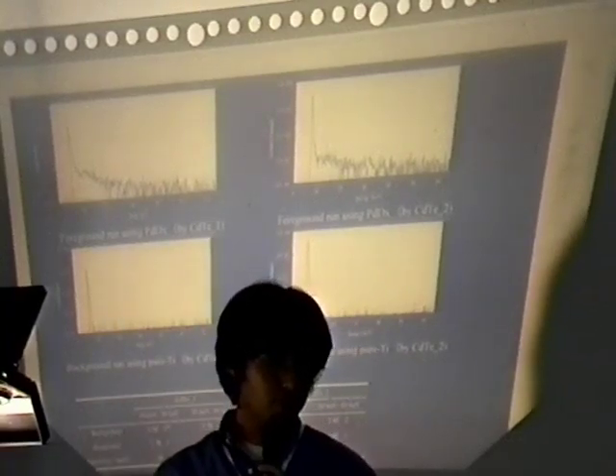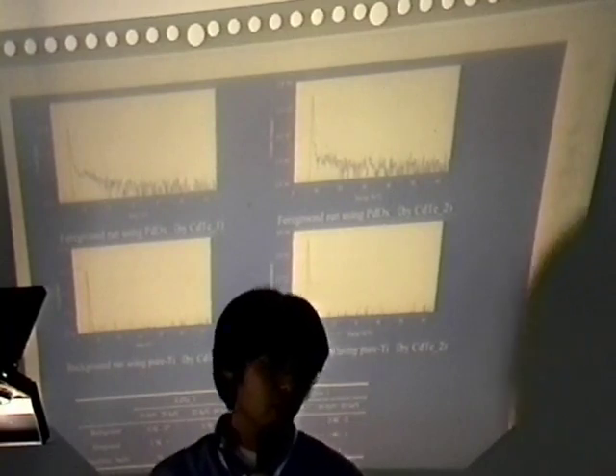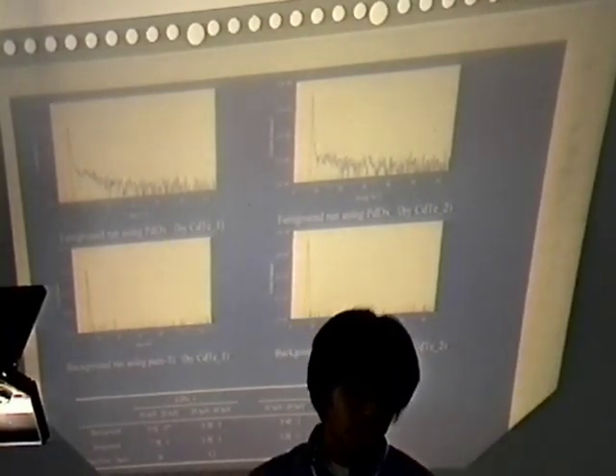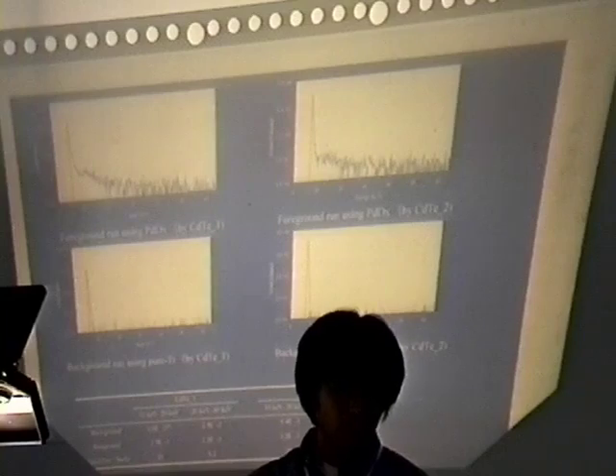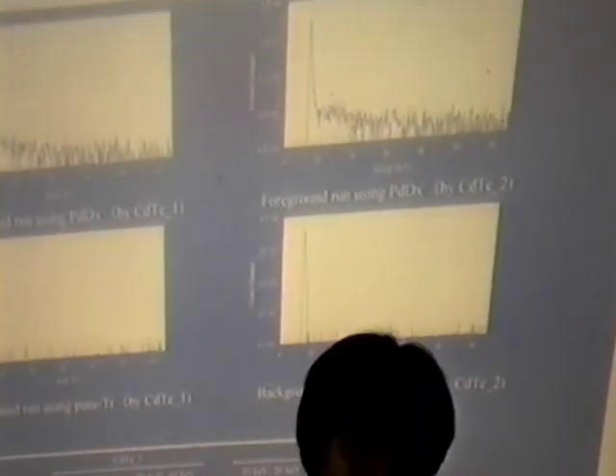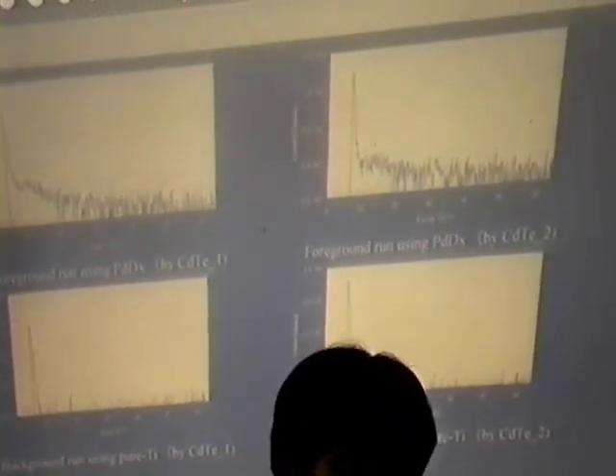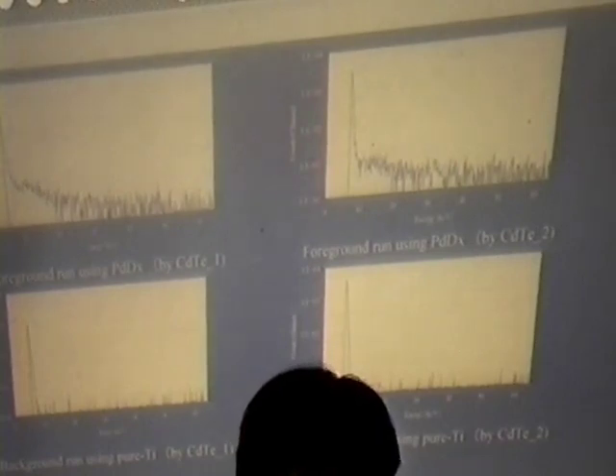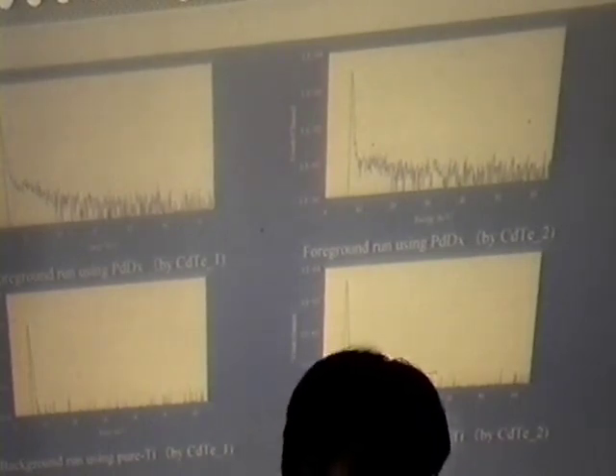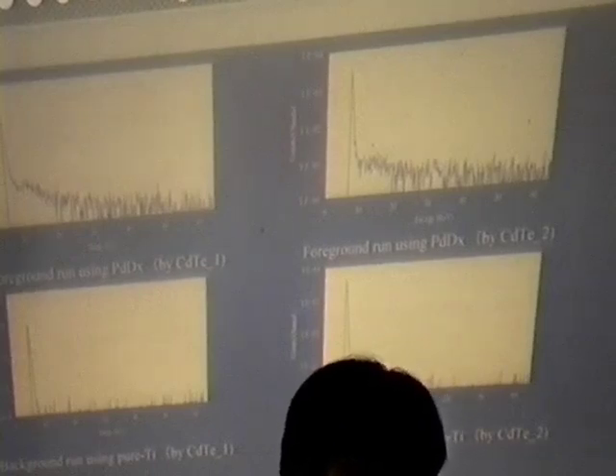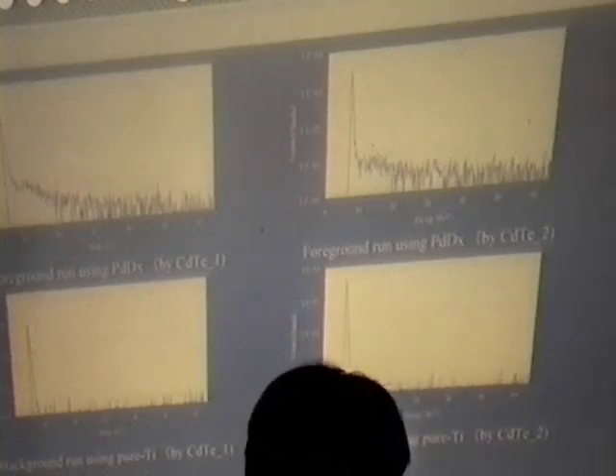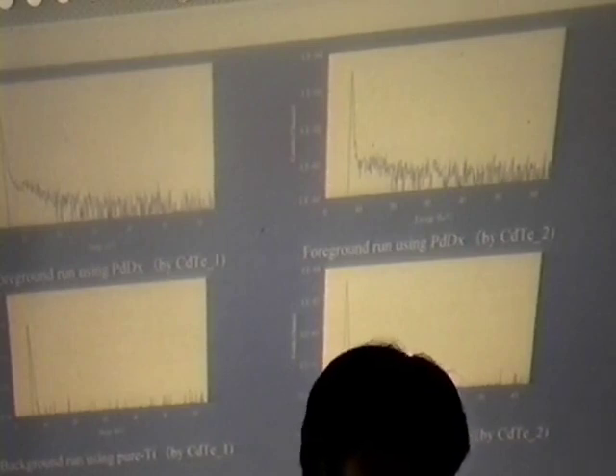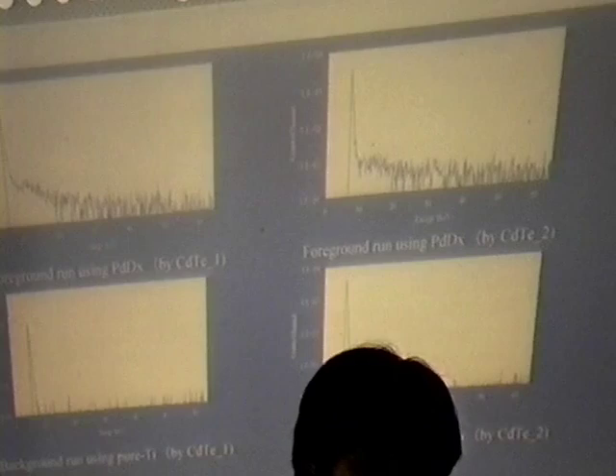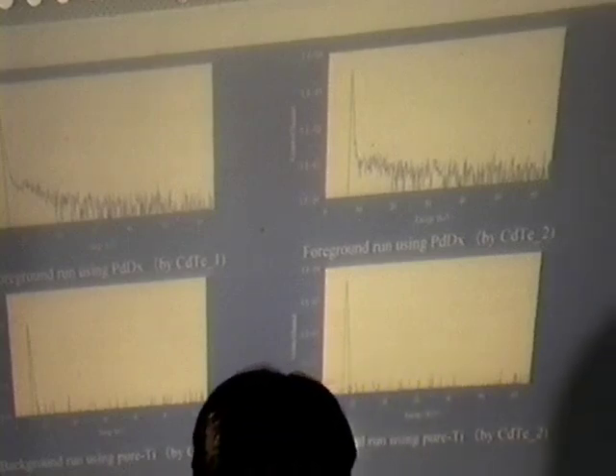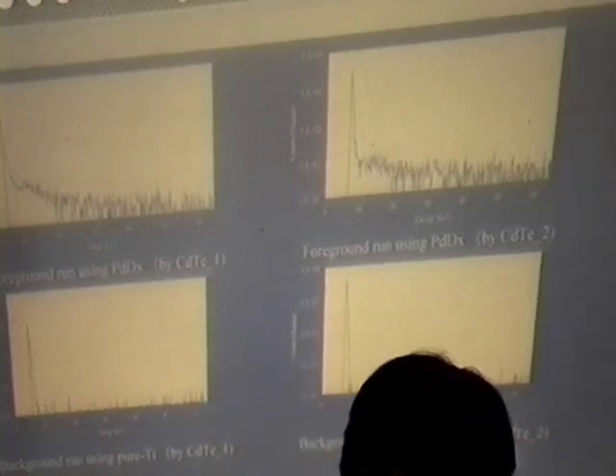And since electron beam energy was about 3 keV, energy of X-rays by slowing down of the incident electron must not exceed 3 keV. And considering that the similar spectra were detected by 2 identical detectors, these spectra cannot be explained by detector's malfunction. And because the energy spectra by SSBDs were same to the ordinary background, these signals may not be electromagnetic noise.